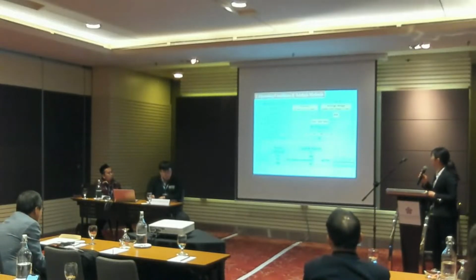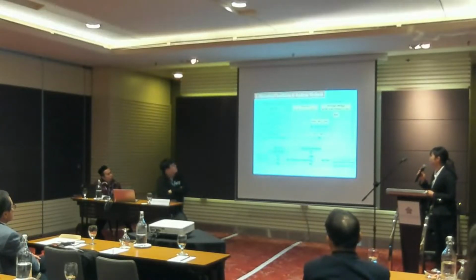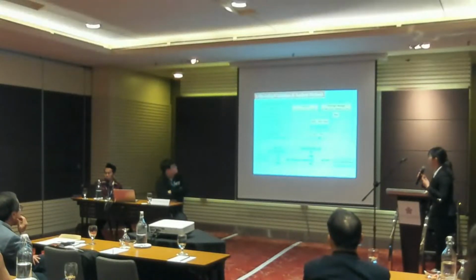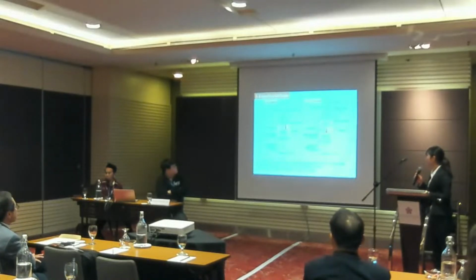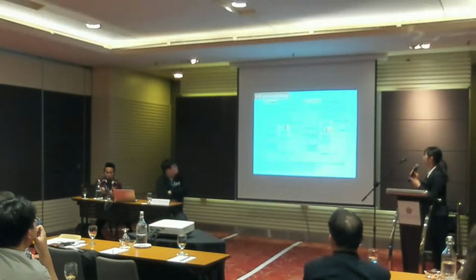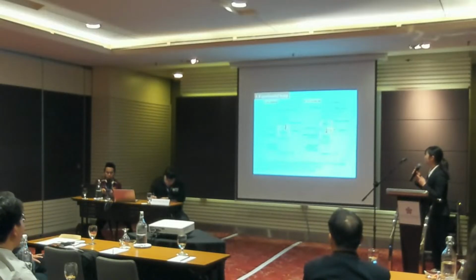This table shows operating conditions and analysis methods. In the actual tar experiment, pyrolysis temperature was 800 degrees Celsius, and in both experiments, reforming temperature was 800, 850, and 900 degrees Celsius. We investigated carbon amount and gas composition, and we identified tar components. This figure shows the experimental setup. Figure A is the setup for the toluene experiment, and Figure B is for actual tar. The actual tar was obtained by granulating the undigested dried sewage sludge into cylinders of about 5 mm and feeding 12 grains every 2.5 minutes.